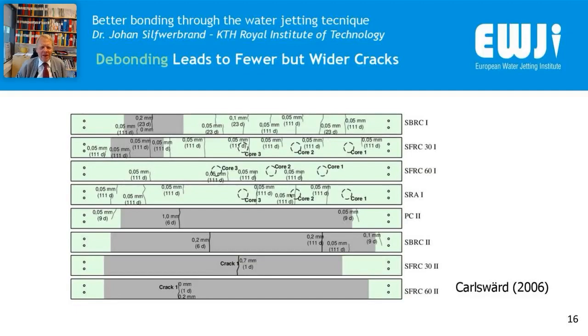But he also tested some of the beams. He deliberately broke the bond, and you can see here the gray area. There are areas without bond between the two layers, and here you can see fairly large cracks, 1 millimeter, 0.7 millimeters, etc., already after the 6 days and so on. And these cracks will continue to grow as the shrinkage develops further. But normally you have just 1 or maybe 2 cracks, and then all deformation is concentrated here. Of course, if you have cracks that are 1 millimeter or more, then that will be detrimental for the durability of your reinforced concrete.